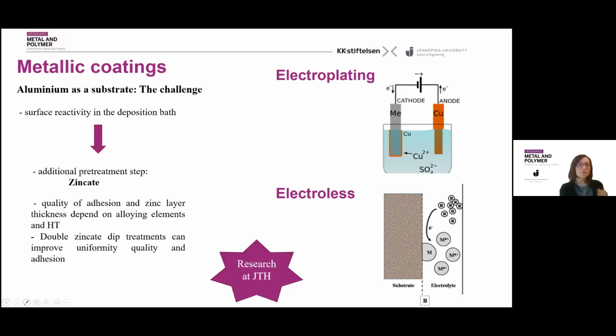The quality of the final metallic layer depends on the quality of this pre-treatment intermediate zincate layer. The quality of the adhesion depends on the alloying element, because the zincate will form mainly on aluminum, not so much on the intermetallic particles. You can improve its quality by making a two-step application.